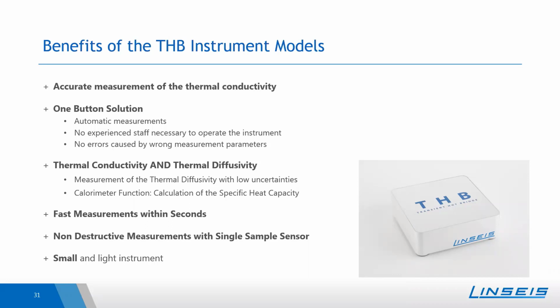A small disadvantage of the THB is that it's not an absolute measurement method, so it needs to be calibrated with a certified material, but the calibration is also not complex. One more or less just performs a classic measurement to be able to calibrate the instrument. We also offer a broad range of calibration materials.